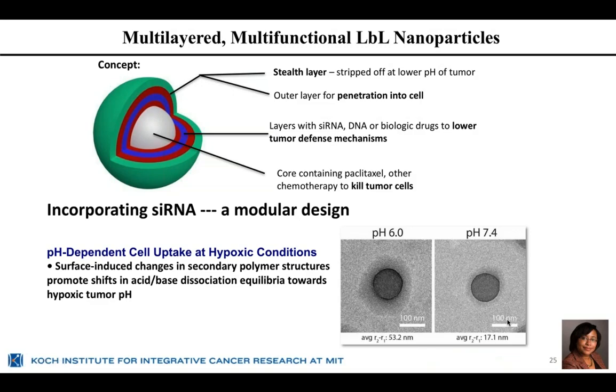Now, that's just one way to get into the tumor. And of course, if we do get in, we have to worry about whether or not tumor cells will actually take up the nanoparticle. And because we've been very careful about disguising these nanoparticles as essentially water-shrouded objects, we need a reason for these nanoparticles to be taken up by the tumor cells. It turns out that one of the mechanisms by which we avoid these interactions with healthy cells is through strong negative charge, and the other is through the shroud of water that we have. At pH 7.4, our nanoparticles have a strong negative charge of about minus 30 millivolts.